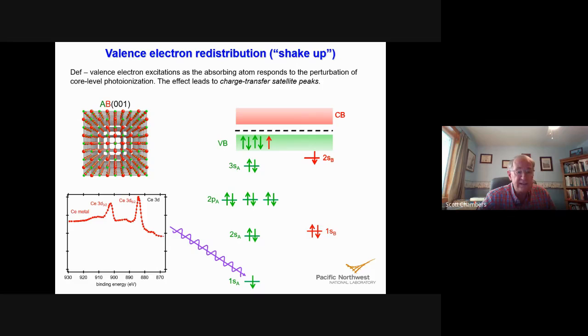But if we look at cerium dioxide, CeO2, notice how different the spectrum is. Yes, peaks have been moved to higher binding energy, as you would expect, because we're going from cerium 0 to cerium 4. But now instead of having 2 peaks, we have 6 peaks. Cerium 4 formally has no unpaired valence electrons, because it's 4f0, 5d0, so angular momentum coupling is not going to happen. All of these 6 different features are due to shakeup. If you didn't know that, you might try assigning oxidation states to all these peaks, and you'd be completely wrong, and you would have missed the physics altogether.